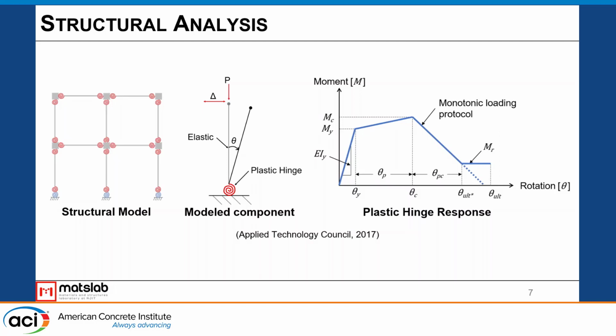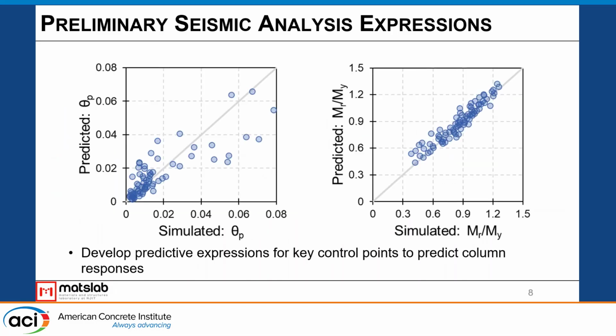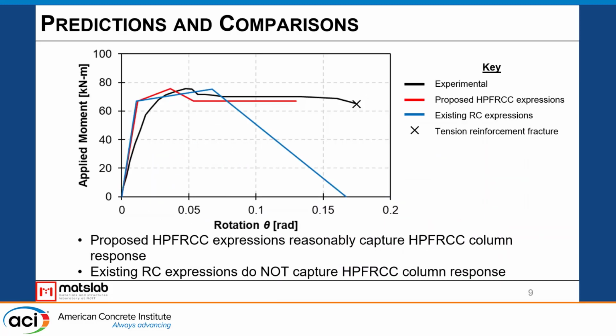And we then just connect the dots to get a rough moment rotation response of that column without actually doing finite element simulations. So we went ahead and created some preliminary seismic analysis expressions for those key control points. And from there, we compared that not only to the very limited experimental data, but also to existing reinforced concrete expressions to see how these materials and how we would model them change. So in black, we have the experimental. In red, we have the moment rotation response predicted from our expressions developed from our finite element simulations. And in blue, we have our reinforced concrete expressions.